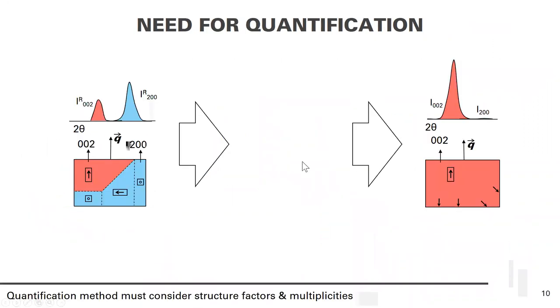But we have a need for quantification. Okay? We can appreciate that in an initially unpoled sample, you might have a relative intensity ratio that's proportional to the structure factors and the multiplicities. Okay? And you may appreciate that under an extremely poled condition, you could have one peak take that full intensity and the other peak go to essentially zero.